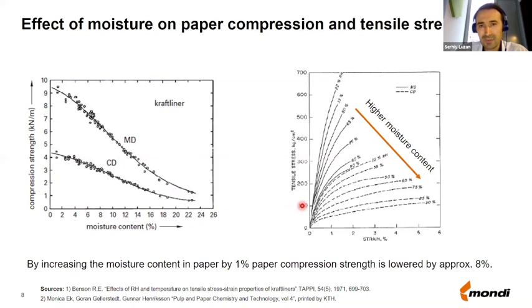On the right-hand side, you see an example of how the tensile properties of paper change with increasing or decreasing relative humidity. If in compression we are compressing the paper, in a tensile test we are stretching the paper. The steeper the line, the stiffer the paper is. And the longer the line, the more flexible the paper is. As you see, when the humidity is increasing, this line becomes less steep, but it becomes longer. So it means that when the relative humidity of the air is increasing, the paper is becoming less stiff, but